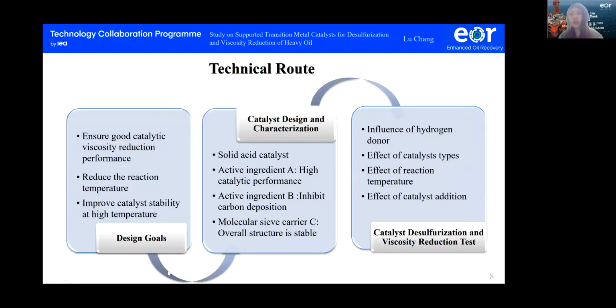And to achieve this goal, we would like to use the solid acid catalyst as a target catalyst, because these kinds of catalysts have relatively good performance and their modification is relatively flexible and easy. 2 transition metal components A and B are selected as active ingredients, and the molecular sieve C is used as a carrier, which can improve the overall structure stability of the catalyst.